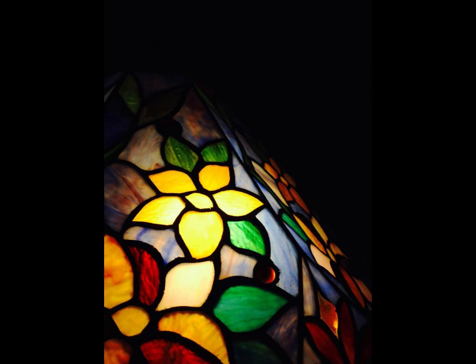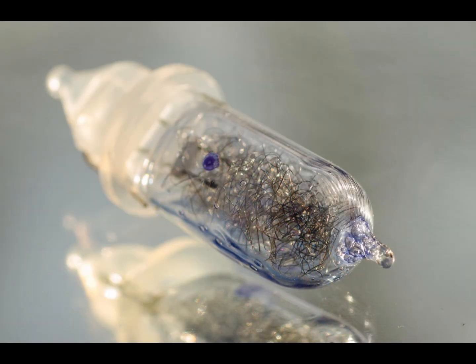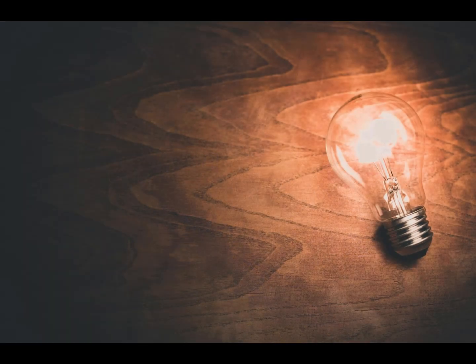A very small amount of water vapor inside a light bulb can significantly increase lamp darkening. Water vapor dissociates into hydrogen and oxygen at the hot filament. The oxygen attacks the tungsten metal, and the resulting tungsten oxide particles travel to cooler parts of the lamp. Hydrogen from water vapor reduces the oxide, reforming water vapor and continuing this water cycle. The equivalent of a drop of water distributed over 500,000 lamps will significantly increase darkening.